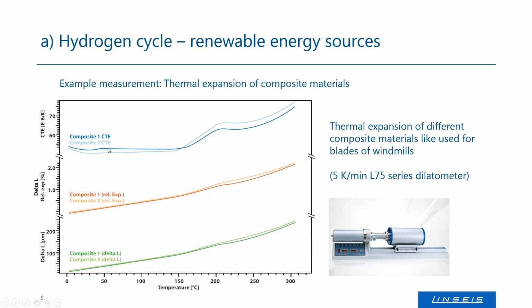That means at that point, there is a little phase transition, a little change in behavior. If you take a look at the CTE, the coefficient of linear expansion, you see a definite change at the first phase transition and at the second. As that's a composite consisting of multiple different polymers, you know that one polymer has a glass transition here, the other one has the glass transition there. And out of that, you can imagine that at those temperatures, the structure and the hardness of the blades could change, which is the information these customers were interested in. They also saw that one material has a slightly shifted glass transition and softening point than the other. So you see an effect from the composition on the mechanical structure and on the mechanical behavior of the material.